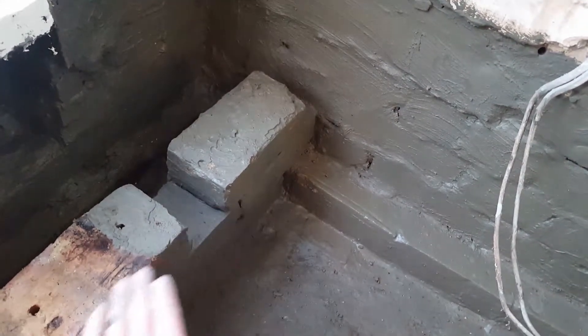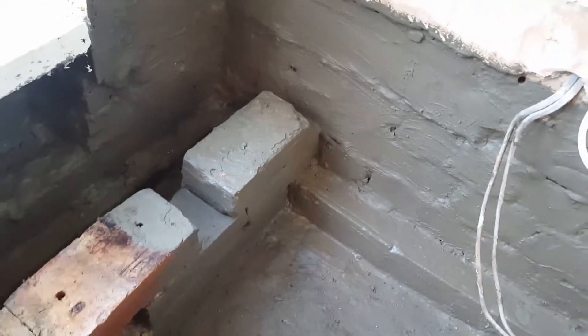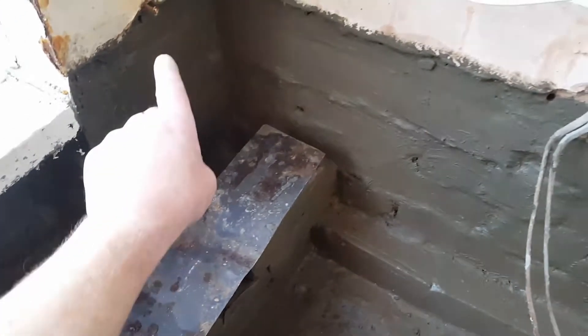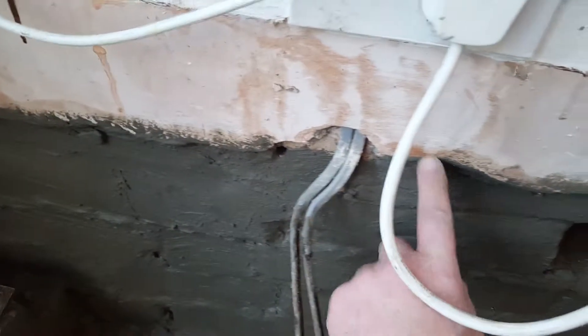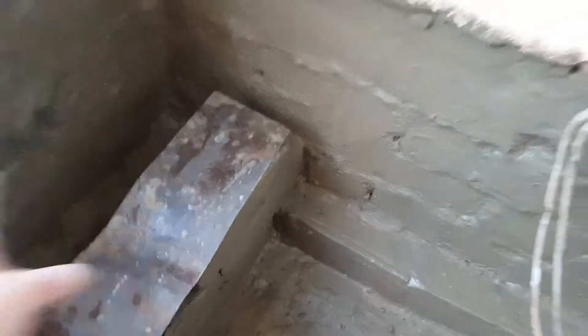There's a screed subfloor and groundwater is coming up through these joist supports and soaking into the joists, even though there's a damp proof membrane. What's happened is whoever repaired this before put the joist touching the wall, and where the joist lands is below the damp proof course in this brick. So the water comes up, hits the damp proof course, stays there, and has been soaking into everything — this corner was particularly damp.